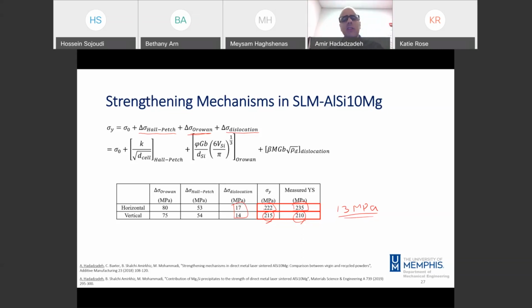Inclusions, we need to make sure that we have a high quality powder where we don't have any impurity in the powder to make sure inclusions will not form. For the surface roughness, again, by using proper process parameters, we can eliminate them. Residual stresses, process parameters, and probably post-process heat treatment. So at least for SLM materials, most of those defects can be controlled by controlling the process parameters. I hope I've addressed the question.